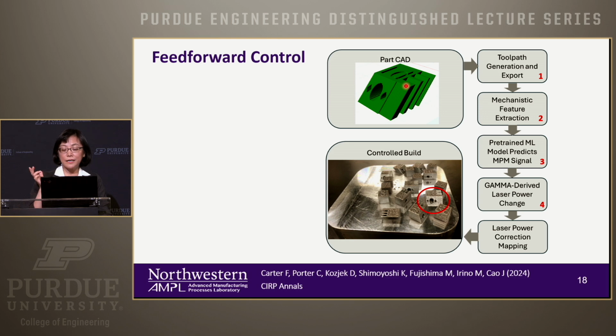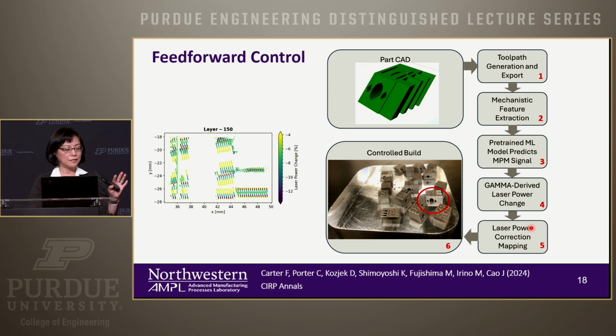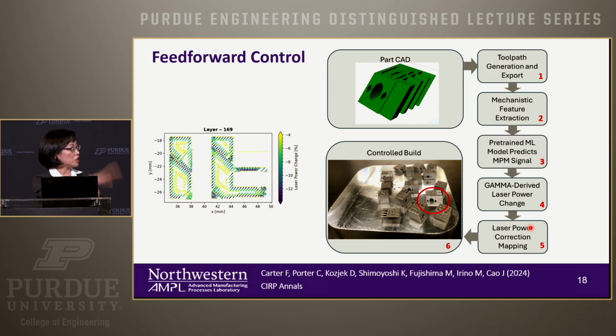And if we see the temperature distribution is actually a signal of those peaks as well, and if we see that there are additional peaks, then what we are going to do is lower the laser power and adjust the laser power accordingly, locally, right? And then using Gamma, an internal code that we developed, we change the laser power, and then we implement it to the real parts, do another build with the laser power not consistent but changing as we go. You can see that this is each layer, how we are changing the laser power.